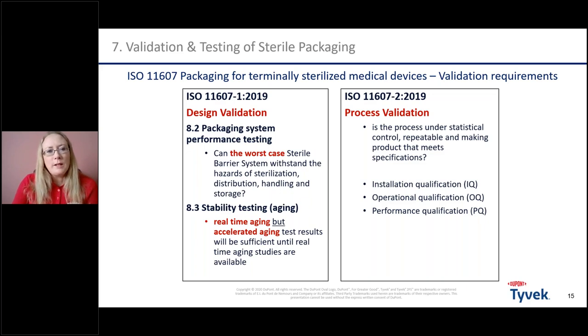But not only that, you should also, of course, validate your design, and this is outlined in part one of the standard. So packaging system performance testing has to be performed, for example distribution simulation on the worst case sterile barrier system, because you need to show that your selected packaging, design, and materials can withstand all the challenges of the packaging life cycle until the point of use. Then stability testing also needs to be done: real-time aging and accelerated aging. Accelerated aging results can already be used to commercialize the product, but real-time aging is necessary as well to claim the shelf life you need to claim. And it's not shown here, but usability requirements and testing are also important to guarantee good handling of the packaging.